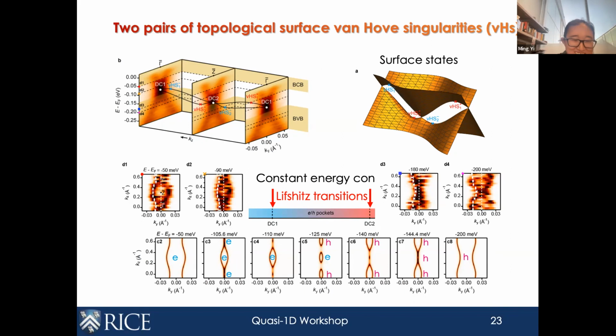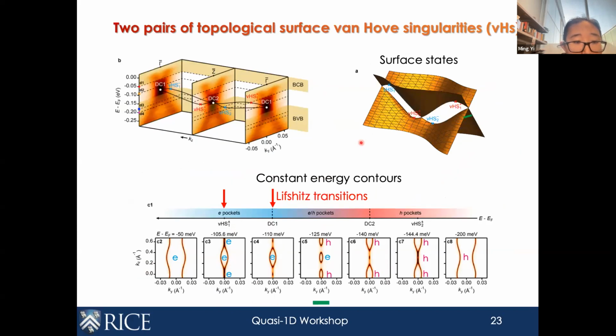I see. Thank you, Nico. Thank you for your beautiful crystals. So based on the location of the two Dirac cones that we observe at the gamma point and the Z point, that means that, consistent with the symmetry of the crystals, we necessarily have this kind of surface state. And this is the higher Dirac cone, this is the lower Dirac cone. And then there is a gap in between. So because of the structure, you can imagine we can walk down by looking at the constant energy contours. You can take slices of this horizontally as you lower the energy, right? So right in the middle around this energy, if you're slicing across here, the pair outside are hole-like, and the pocket you have in the middle will be electron-like.